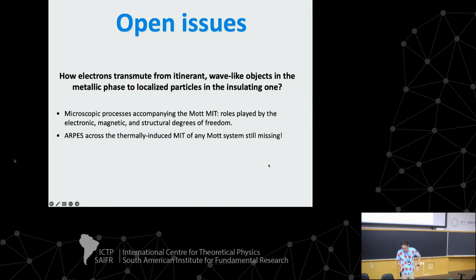Okay, but so far, one big open issue, experimentally, without trying to put any theory behind this, a very simple question: how do electrons go from that free-electron-like parabolic dispersion that I showed you in the metallic state to localized particles, because if the system goes to an insulating state, particles need to be localized. And actually, this had been impossible so far for a very simple yet annoying reason. The structural transition in V2O3 is so strong that single crystals break apart into pieces when you cool them down. And when this happens, you cannot do ARPES anymore.